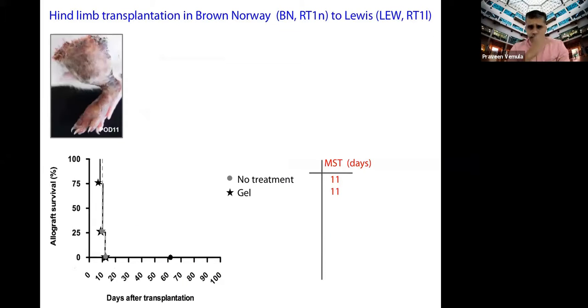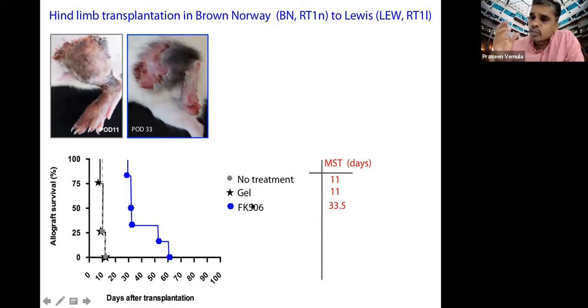Okay, just to quickly summarize the main results. Once you do the surgery, if you don't give any treatment, or you inject only gels without the drugs, within 11 days, 50% of the animals reject the graft. As you can see, severe inflammation in the tissue and grade 1, grade 2 rejection in these animals. Now, as a control, we take only the drug, tacrolimus, without encapsulating it, and do a local injection. In that case, you can see within 33 days, they start rejecting the graft completely. We can see severe muscle tissue damage, high inflammation and grade 3 rejection.